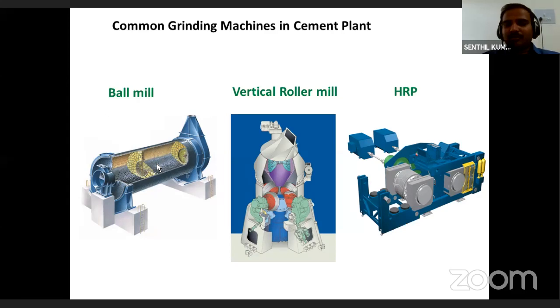So they are my known factors. So based on that, the regradation or the top up we decide. And then for the liners, we go for periodic inspections inside the mill, and we measure the thickness, and then we check it, and then we replace the liners after 3 or 4 or 5 years. So that's for the ball mill.